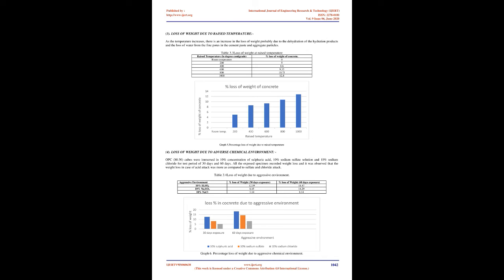2.2 Testing method for adverse chemical environment. 6 cubes of M30 coconut fiber concrete were immersed in 10% concentration of sulfuric acid, 10% sodium sulfate solution and 10% sodium chloride, each for test periods of 30 and 60 days. To avoid settling of the solution, the solution was mixed every 7th day. Once the test period was over, the specimens were taken out and left at room temperature for 3 days, then kept in a heat curing chamber for 2 hours to dry. Afterwards the specimens were tested for change in compressive strength and change in mass.